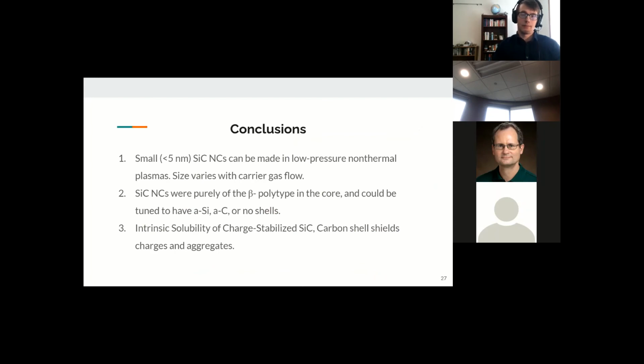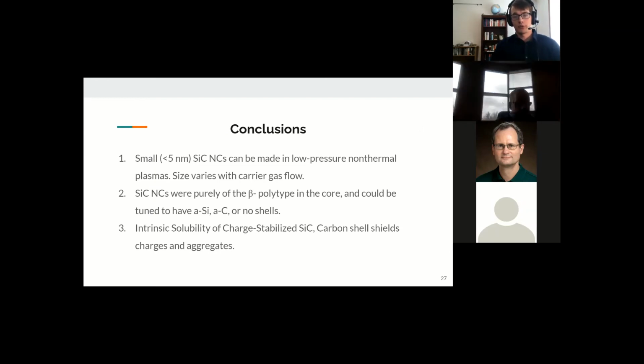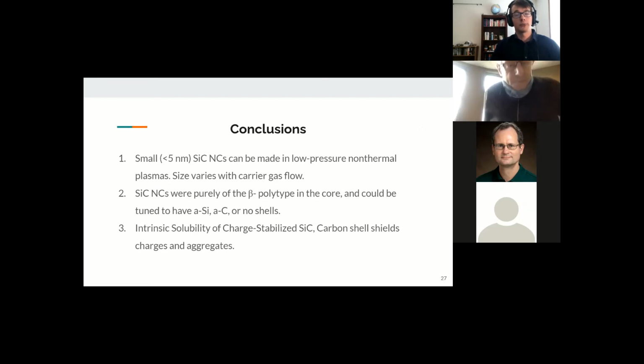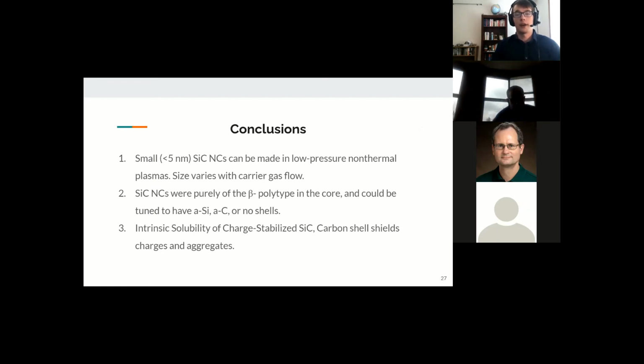In this study, beta polymorph small silicon carbide nanocrystals were made in a low pressure non-thermal plasma reactor. Silicon carbide nanocrystals of this size have never been made with this method before. The radii of the nanocrystal spheres were varied by changing the reactor pressure and the precursor flow rates through the reactor, and the sizes were confirmed by both XRD and TEM measurements.